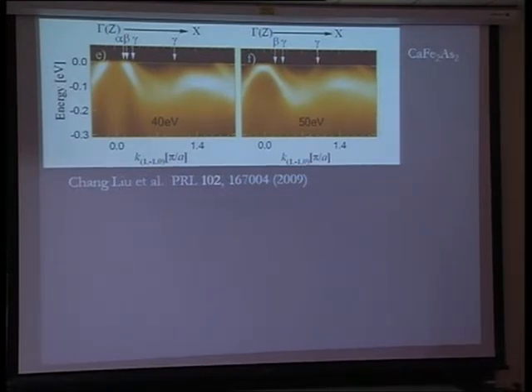I just quote this paper, where you can see that this is the K vector, along the K11 by 0 direction, and this is the gamma point, and there appear to be three bands, alpha, beta, gamma. Alpha crosses the Fermi level close to the gamma point, and you have this beta and gamma band. And your X point comes here, X is almost the Brillouin boundary along this direction. And one thing you can see is that this is at a low temperature, I think about 15, 12, I'll check the temperature later. So at low temperature, which is within the spin density wave phase.